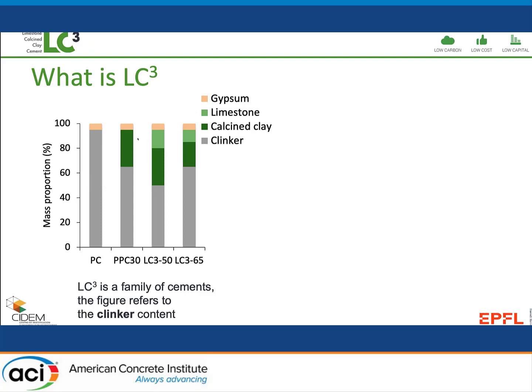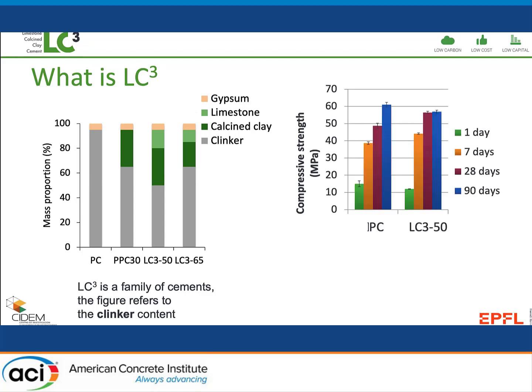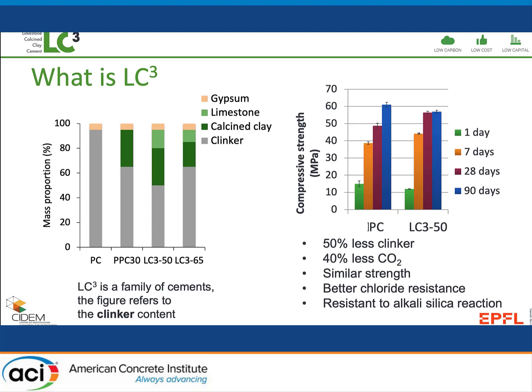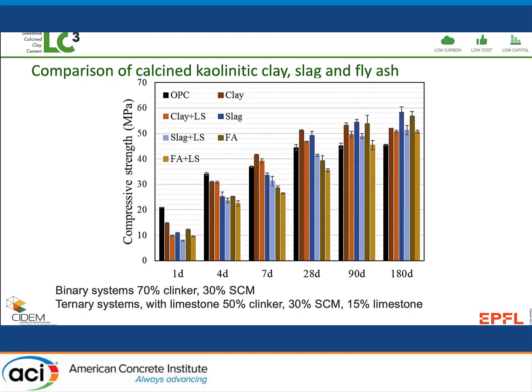Now with a new European standard, we can go to 50%, and we actually know we can get good properties even with 40% clinker. And if you have a good quality clay with a large content of kaolinite, you get a very small reduction at 1 day, but by 7 days, you have a higher strength. So you have 50% less clinker, 40% less CO2. This takes into account the energy to calcine the clay, similar strength, and some properties like chloride resistance and resistance to alkali silica reaction are greatly improved. I'll come back to that.